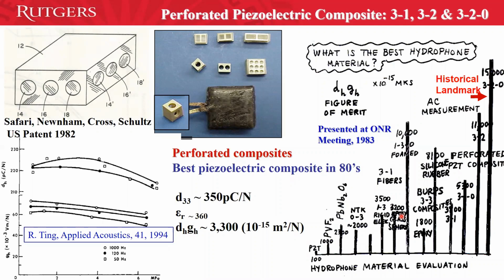So I was always thinking, okay, how can I make the inverse of the PZT sphere? And so I came up with this type of composite. This is the patent. I believe this is the second patent for the Ferroelectric Group at MRL. The first one was the 1-3 composite by Klicker. This is called perforated. We can have this in 1-3, 2-2, or 3-1, 3-2 connectivity. Less pressure sensitive, but very high dh and very high gh, and the product of dh and gh is 15,000.